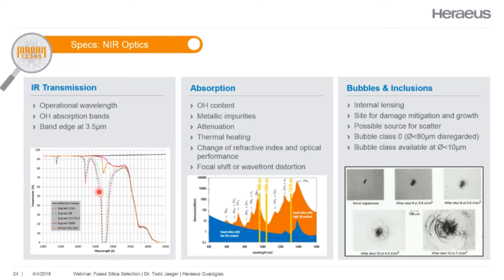These are materials that are higher in OH, and in the infrared, the OH is actually going to absorb. We show that over here in the absorption. We have in the blue a fused silica that has a low OH content, and in the orange is a fused silica with a high OH content. These are absorption bands from the OH itself, and then we've overlaid a few of the common laser wavelengths. So you can see that on any of these wavelengths, even at 1064, there is some absorption, and in some cases significant absorption on these laser wavelengths.